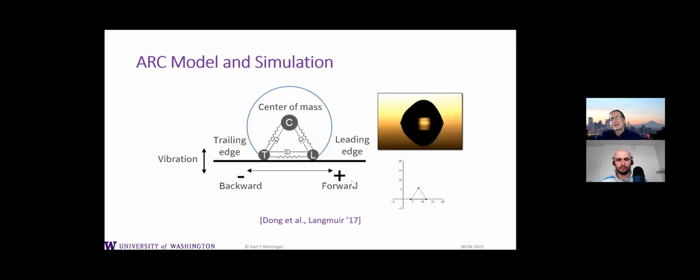If you model that, then you can actually show that the anisotropy of the surface translates into a lateral force that makes the drop move from, in this case, left to right. And here, since it is a ratcheting motion, there's no limit on how far the drop can move.